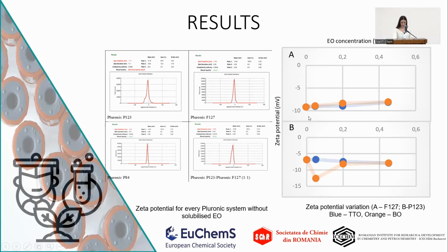On the right side of the slide, there is the zeta potential as a function of essential oil concentration. Again, the essential oil concentration didn't actually affect the stability, nor make it more stable or unstable. It just remained the same, with one exception right here in the case of the P123 system with the bergamot oil. The zeta potential is actually a bit lower, which means that the system may have suffered, again, a breakdown.